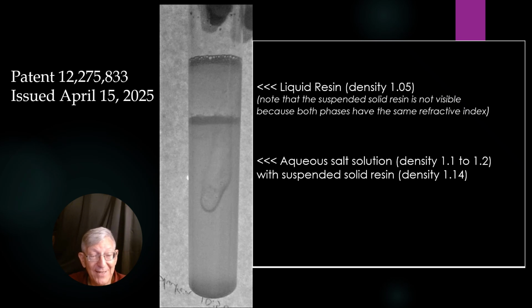That's a problem. But then you'll notice there's no supports, and so there's a gravitational issue: if you got it out of the resin and set it on a table, it would probably crumple down, because until the resin gets a chance to fully solidify, it's still flexible and still gets moved and bent. And so what we've done here, we've eliminated both of those problems. First off, the sinking process tends to be slow and progressive, and so that allows you to avoid viscosity drag, which would cause deformation of your material. And then, because you're sinking into a density gradient, you essentially avoid any substantial gravitational deformation of the object that you have created.